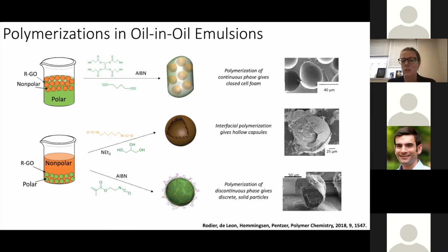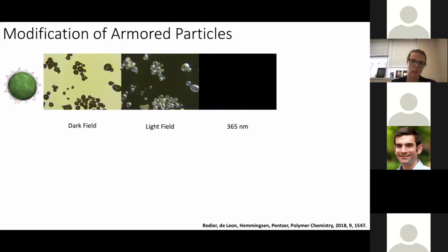You see from the SEM on the right in the center that the hollow capsule is actually collapsed within the SEM. And then on the bottom right, he could also make these solid polymer particles. So he's cut the front end off of that particle to show that it is indeed solid all the way through. And so one thing to note is that the isocyanates on the methacrylate are retained after polymerization because we're in a water-free environment. And we know that they're there also from FTIR spectroscopy.